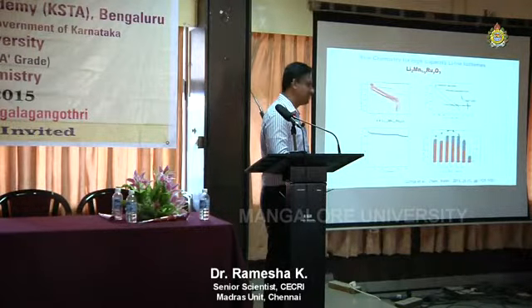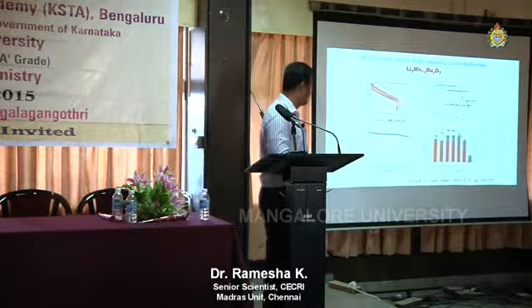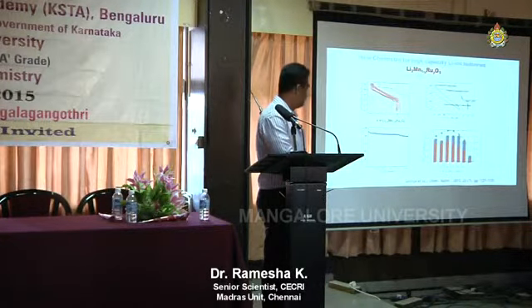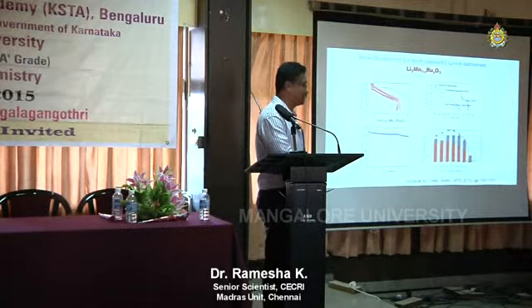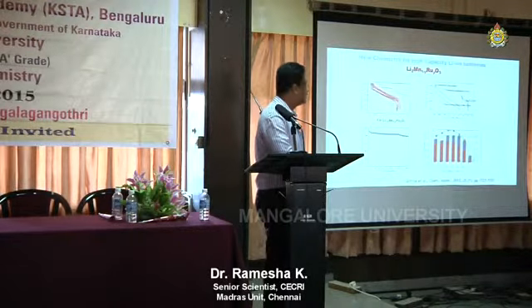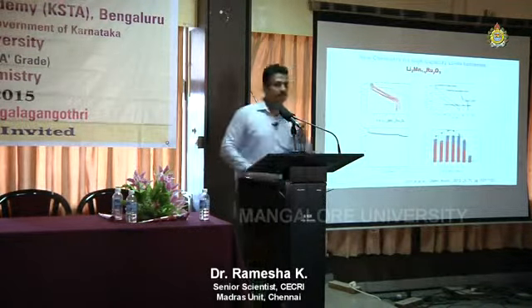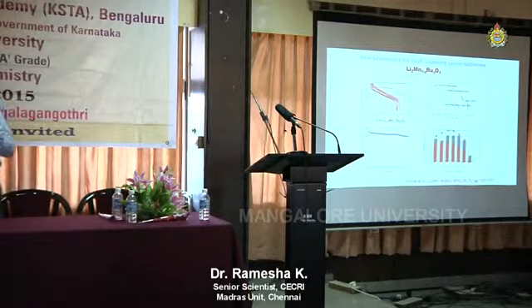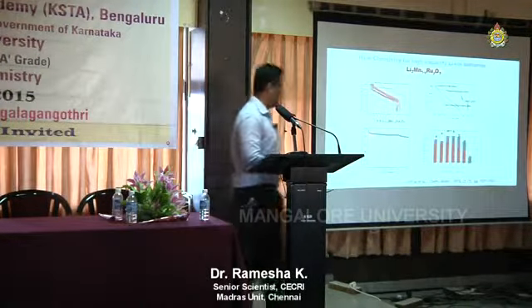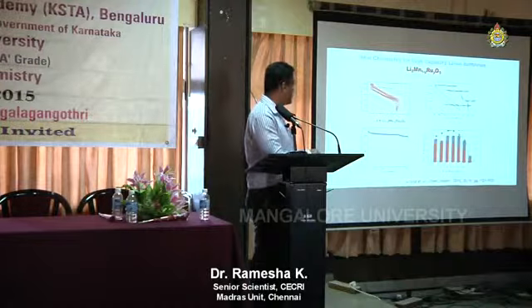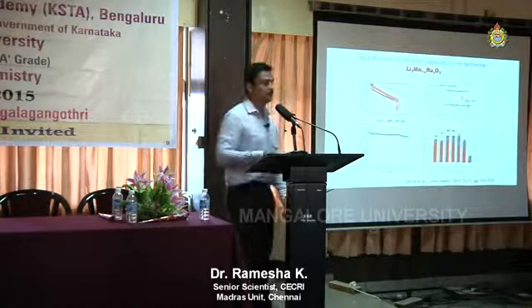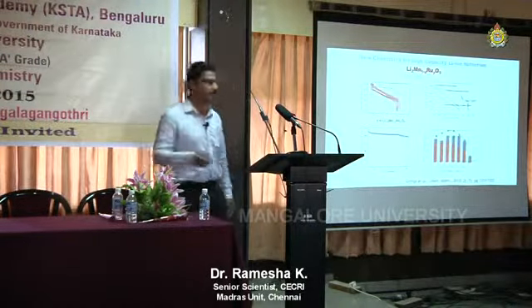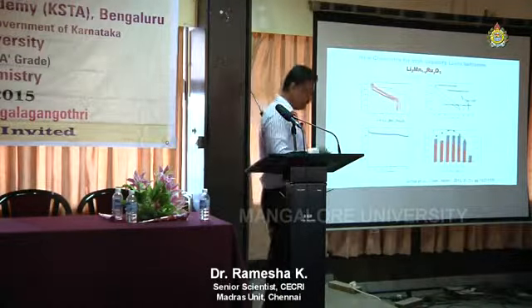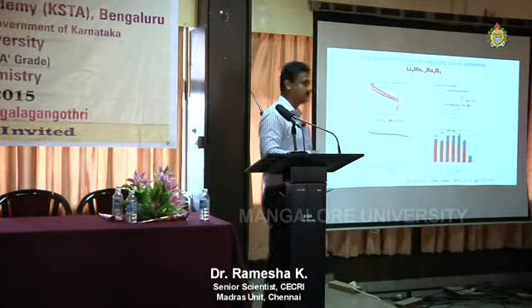This is the number of cycles, 50 cycles, 100 cycles of charge and discharge. Definitely above 140, right? Somewhere 220, 230. Okay. So this is the new material which we doubled. See, even a small increase from 140 to 150, the industry will be very, very excited. So something similar to that, we showed that this material shows almost double the capacity compared to the known lithium cobalt oxide material. Of course, the issue is again the ruthenium is more costly.